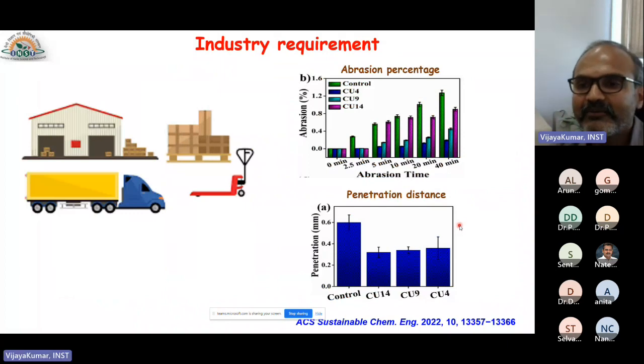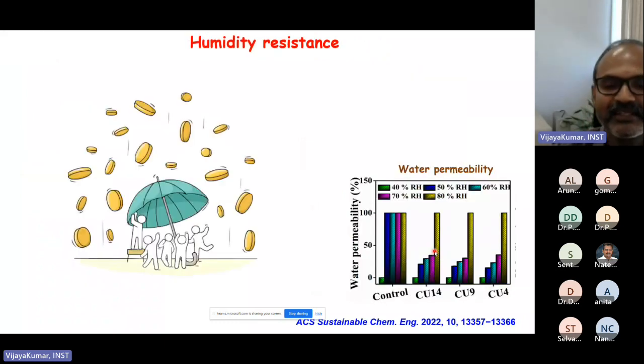Now with these three coating materials developed with different coating strength, we checked the abrasion, and we were able to see that the coating with 4% and 9% is able to overcome the abrasion given through the zirconia milling. Whereas the 14%, which is so thick, is fragile, and it shows almost the fragility of the control, which is also broken by this abrasion disturbance given at the lab scale. In the penetration distance measured with the penetrometer, all three coatings are able to withstand the penetration. So basically it is stable.